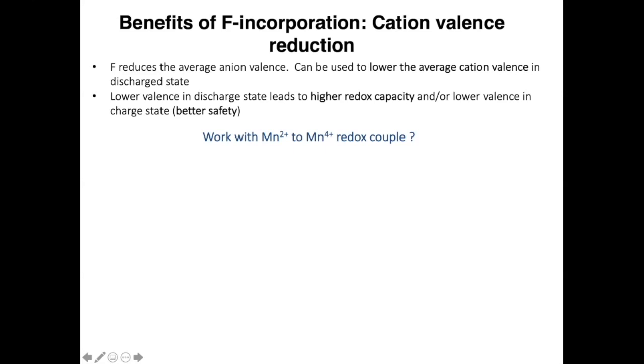So we were even able to lower the valence in the synthesized material so much that we could use manganese too. And this is important because in nature, there are not many double electron redox couples, right? There is, of course, nickel, which is the most important ingredient of NMCs. And then there's vanadium, which we can't really use in layered materials, but others have shown you can use in polyanion materials. But very few people have used double redox on manganese because most of the time we synthesize materials